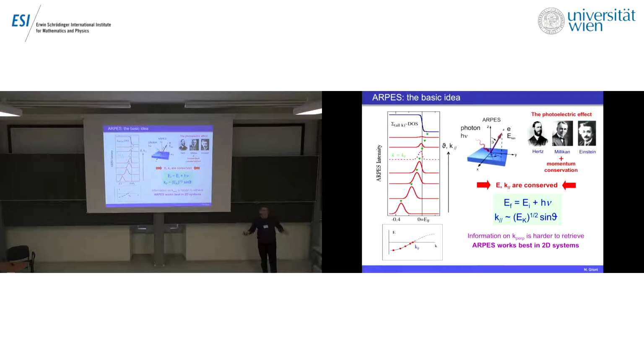So you probably know that photoelectron spectroscopy is based on the photoelectric effect, explained a long time ago. And at this time, actually, people realized that energy was conserved in the process of emitting an electron from a solid after shining monochromatic light on it. Now, what we do today, many years later, is to add momentum conservation. Turns out that in the process, the momentum of the electron is conserved, or at least a component of the momentum of the electron parallel to the surface of the material is conserved. And then by using energy and momentum conservation and simple algebra, one can derive information on the electronic state in the solid before the electron was extracted. Essentially, one can measure the initial energy and the momentum inside the solid.